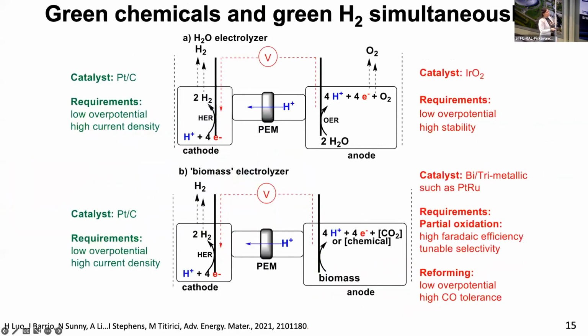As I said, doing this would be highly advantageous compared to water because you won't need iridium oxide to do this, so you lower the costs. However, you'll see that it's difficult. People use platinum ruthenium. I didn't use this. And you will have a higher CO tolerance, you'll have lower overpotential here. And you could also tune the selectivity of the glycerol oxidation to get the product that you want.